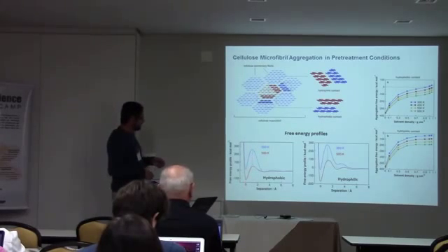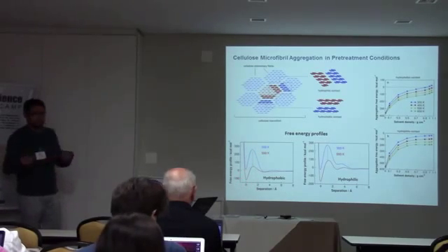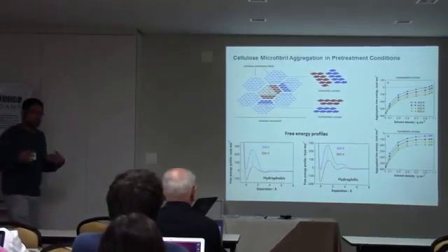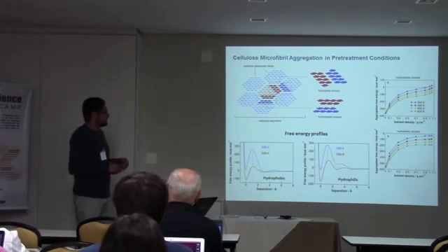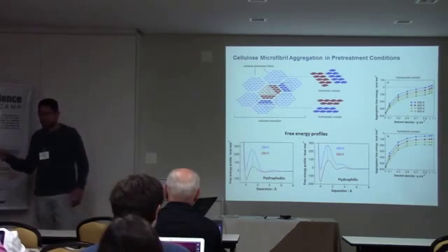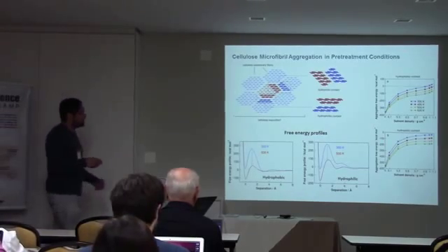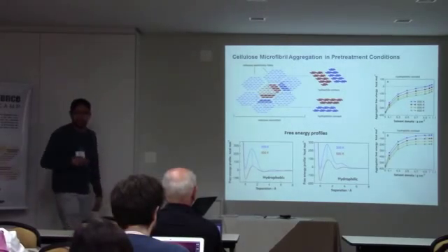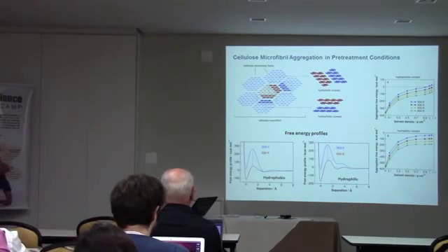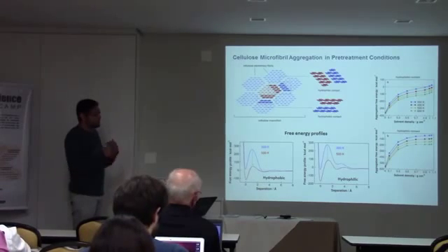And from this free energy profile, we can also obtain, for example, the free energy of aggregation in a lot of different conditions. And this is what I show here, for example, in a range of temperature and a range of density that covers different pre-treatment conditions. And you can see here that, again, the hydrophobic arrangement is much more sensitive to changes in the thermodynamic conditions, and the hydrophilic arrangement can also change qualitatively.